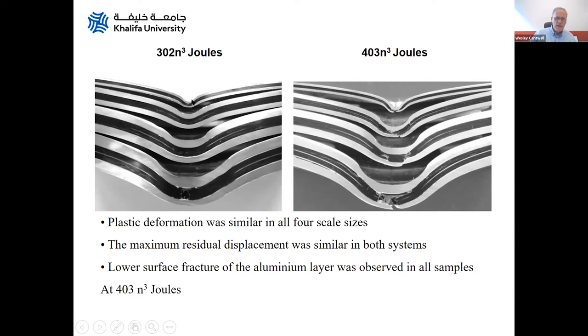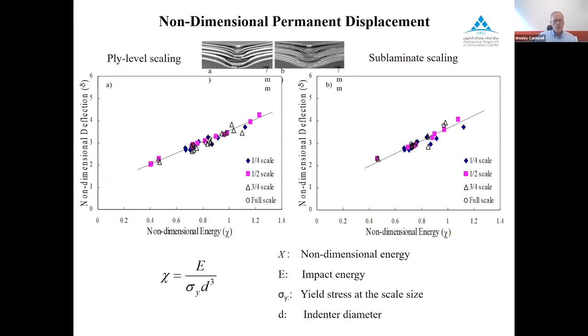So this is a much lower energy, but the same scaled energy. And we're getting very similar levels of damage. And go a little bit higher, 403 N cubed joules. Again, we can see similar failure mechanisms in all four scale sizes: fracture of the lower surface here, and some thinning. You can see this thinning of the plies more clearly here. So great similarity in terms of failure mechanisms as well.